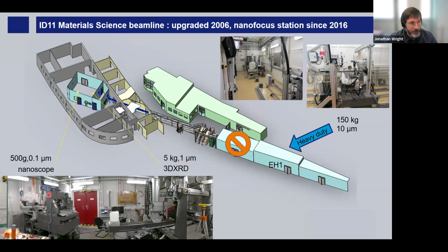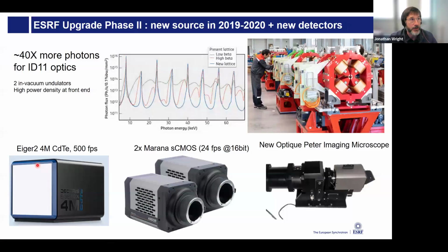Our latest station, this nanofocus station, was installed in 2016. And with this station, we can get down to 0.1 microns, that's about 100 nanometers. But now the sample size is limited to 500 grams. So we have this suite of diffractometers that are trying to map onto different sample dimensions.